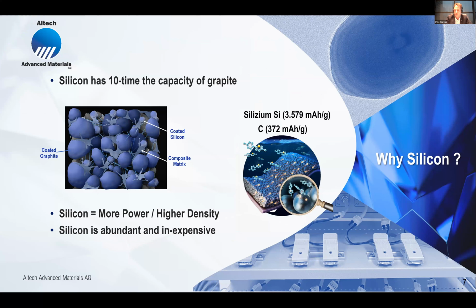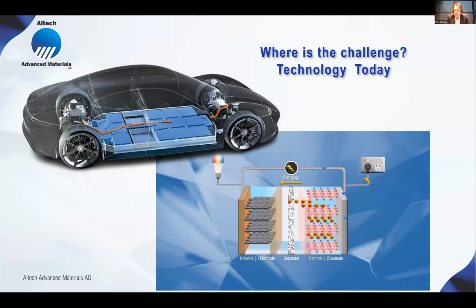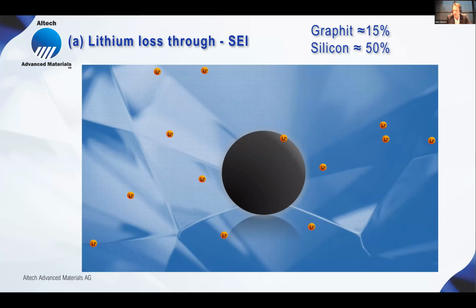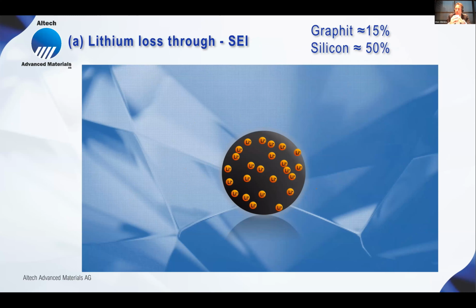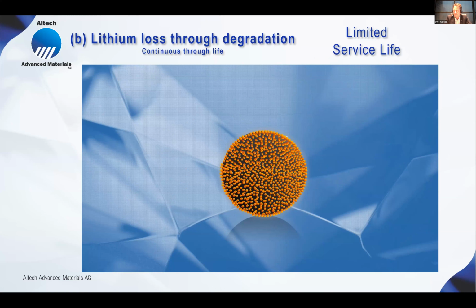So if it's so good, where's the challenge? Well, the challenge is in the battery itself. You see below, all batteries work the same. You have a positive side with the cathode, with a different type of composition, and on the left side, you see the anode, which is graphite or silicon. Now, what happens when the lithium ions go over? They form a solid electrolyte interface, a first layer. They form around the graphite or the silicon, they form a first layer. Now, in graphite, you lose 15%. In silicon, you lose 50%.